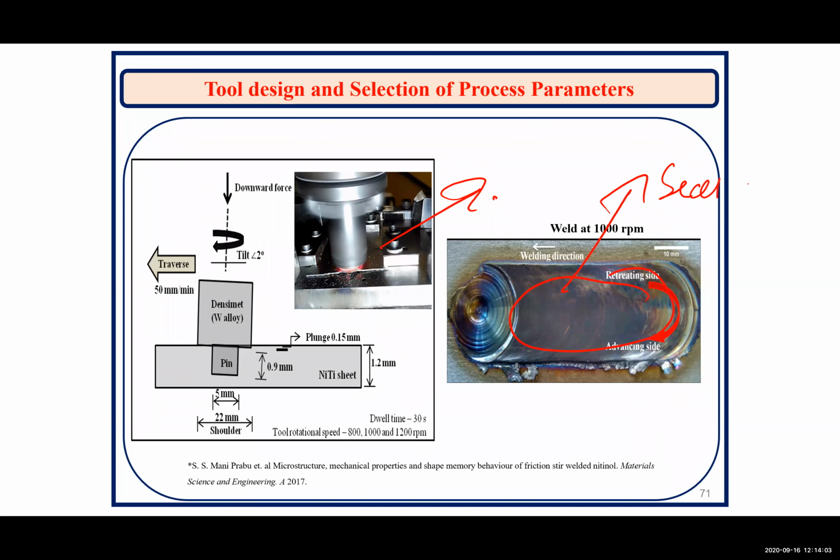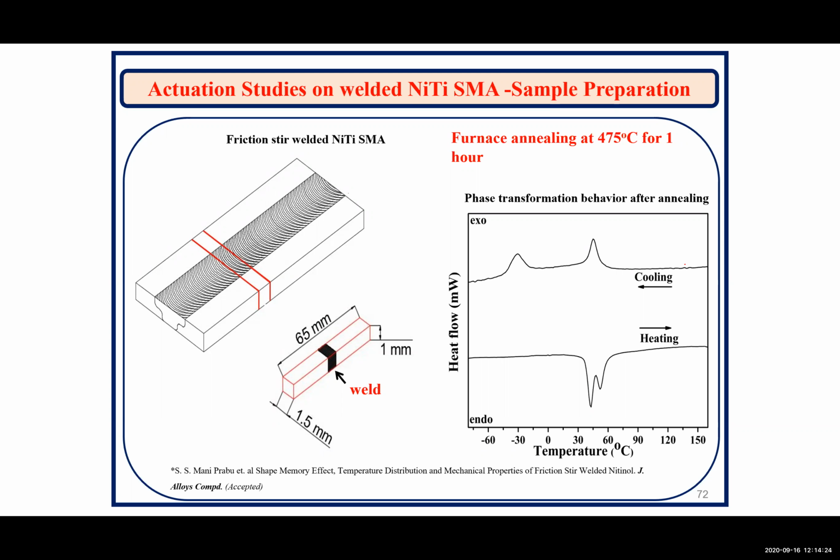was achieved with this NiTi shape memory alloy structures, and then we were trying to study the transformation behavior of these welded structures, because I am more interested in the welding joint, how the welding joint behaves with respect to the cyclic load. So we did a complete friction stir welding of it, and we went for a complete differential scanning calorimetric analysis. In this differential scanning calorimetric analysis, we went for the austenite and the martensite analysis.